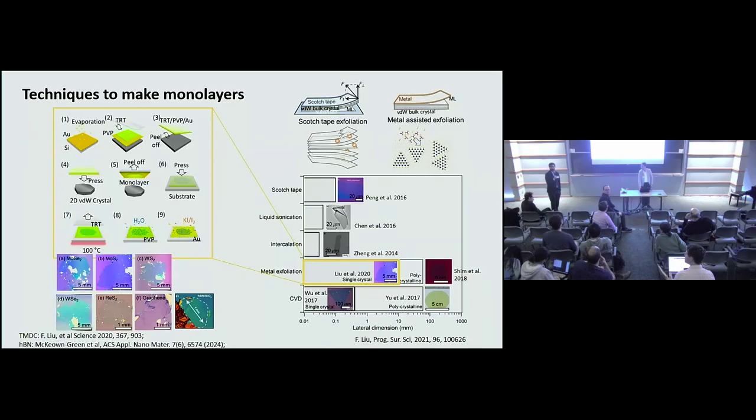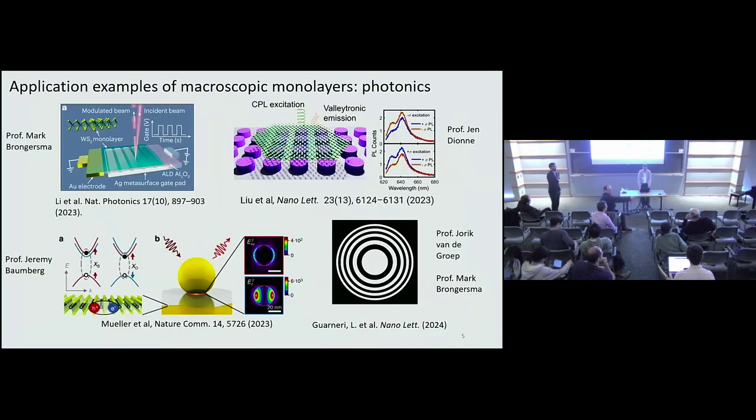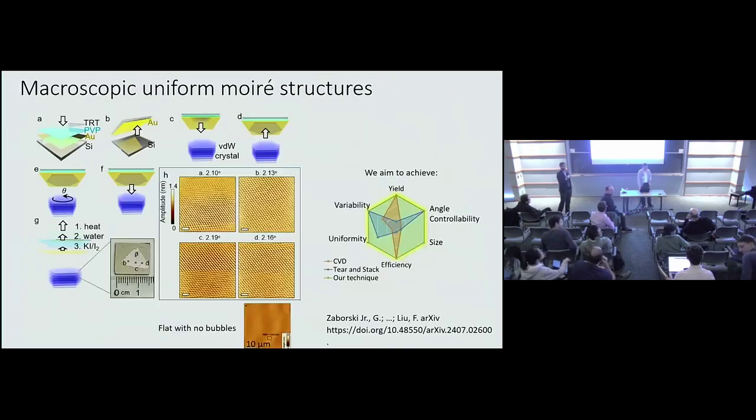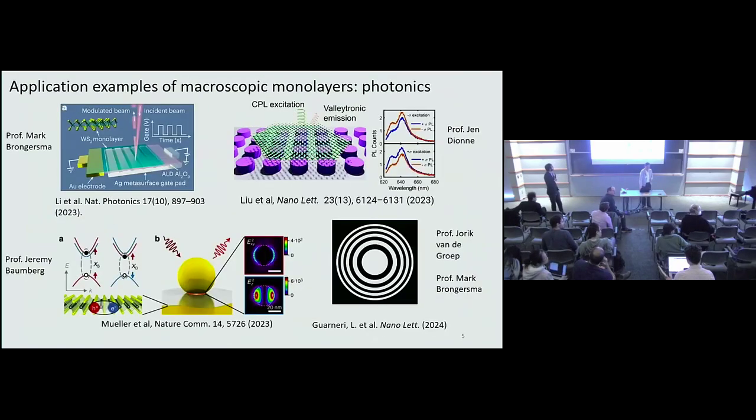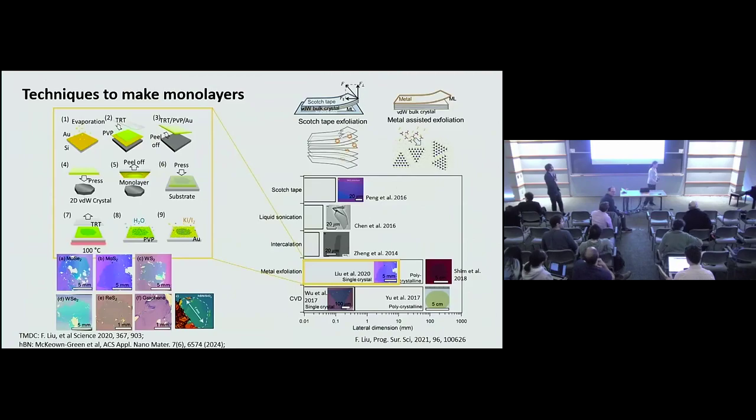Any further questions? So you're saying for HBN you can only get monolayer, but not thicker HBN? We can only get thin layer HBN. For different metals, we can get HBN from single layer to 5 layers, up to 6 and 7 layers. But we cannot get thicker.